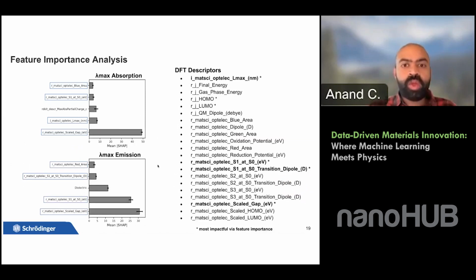So we can look at what are the most important descriptors for these optical properties. For example, for the maximum wavelength of absorption, this is the property that we're trying to target. This is the experimental property. The most important property was the scaled band gap, which we calculated with DFT. And the second most important property was the lambda max absorption that we calculated with DFT. So it is not surprising at all that these highly customized DFT descriptors are the ones that are most important for these optical properties. This shows you how powerful physics-based descriptors can be in calculating these optical properties.